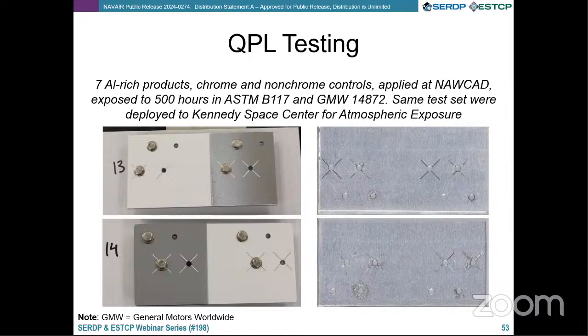Originally, you see there's 8 holes on those panels. Originally, we had included both stainless steel and titanium fasteners. In wanting to simplify things for the coating manufacturers and other test sites who may want to perform this, we found that in no case over the last 10 years has the couple between titanium and aluminum, that's 2024 as a substrate, versus stainless steel and aluminum, ever shown a change in coating performance at protecting corrosion from one type of metal couple versus the other. So we were able to show that you can use a cheaper, simpler mock-up of a panel.